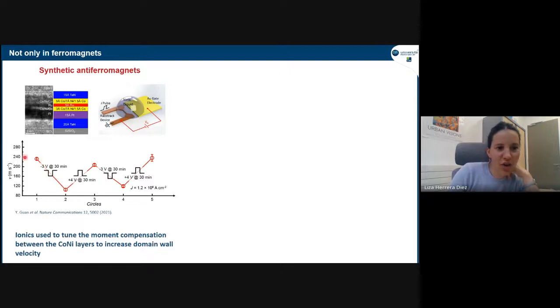So then they go from a very high domain wall velocity to a much, much lower state. So this is a variation of hundreds of meters per second. So this is a very nice way to show that this can go beyond the changes that we can do with anisotropy. This is really something that starts being really relevant for applications. So this was a really neat way of controlling domain wall velocity, not just changing anisotropy as we would usually do or as has been done a lot in the literature.